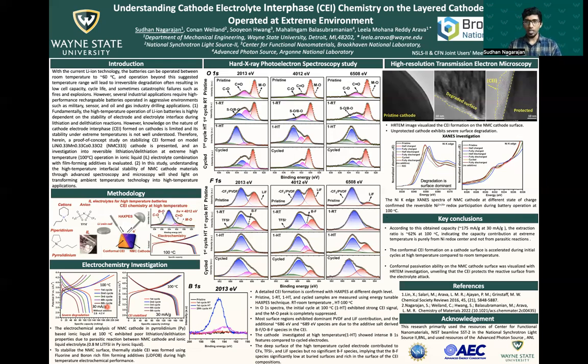So after several studies, we hypothesized that if we stabilize the NMC surface using a thermally stable cathode electrolyte interface, that will reduce the direct contact between electrolyte and cathode surface. So that will improve the electrochemical reactions. So we attempted that approach, and the approach was successful. After adding LiDFOB, lithium difluoro(oxalato)borate, one of the additives in the lithium battery community, that additive improved the performance at 100 degrees Celsius.